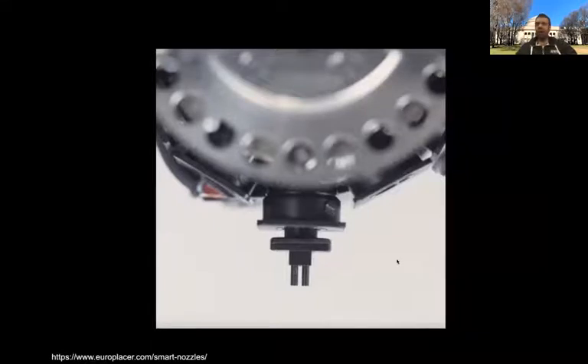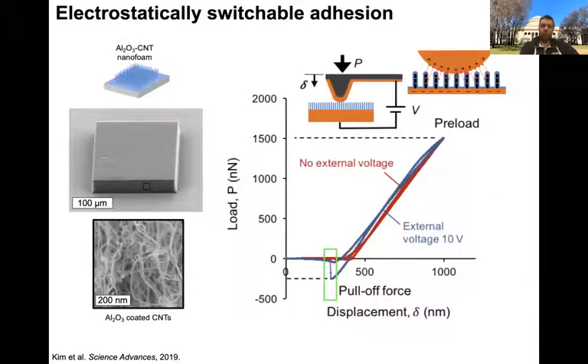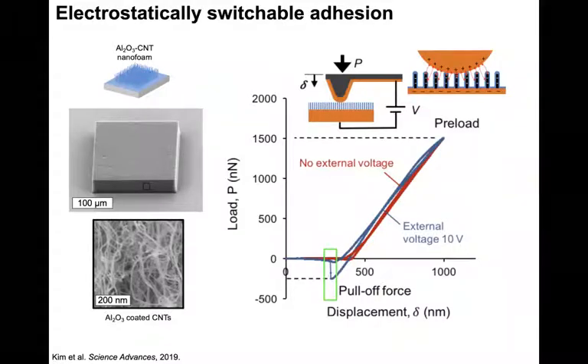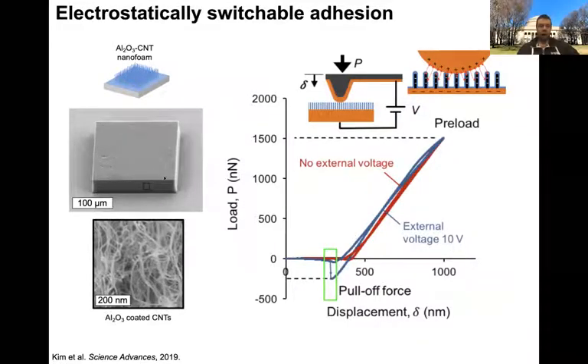So at a later stage of this flexography work, we started thinking of, could we use CNT forests for dry transfer printing and do dry transfer printing with the aid of electrostatics. So here I show you a basic experiment using a CNT forest pillar, just this block you see here, where the CNTs are not coated with a polymer as before, but they're coated with a thin ceramic, also a dielectric. And now we approach the surface of the forest with a scanning probe tip, an AFM tip with a microscale radius, and look at the force displacement curve, what we call the pull-off force curve, without voltage and with voltage applied, say a voltage of 10 volts.